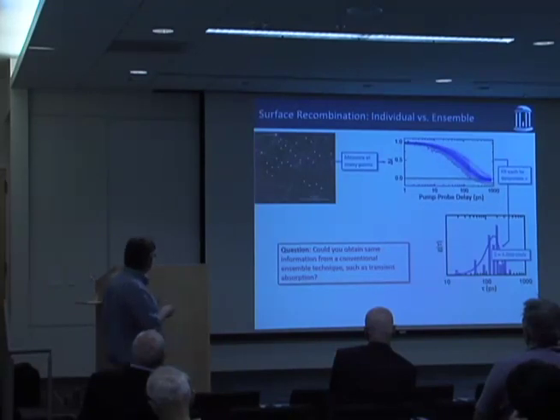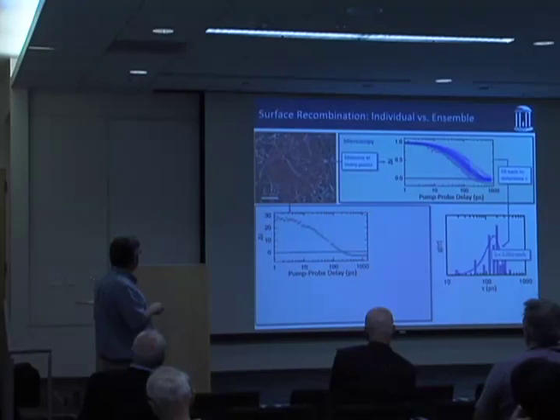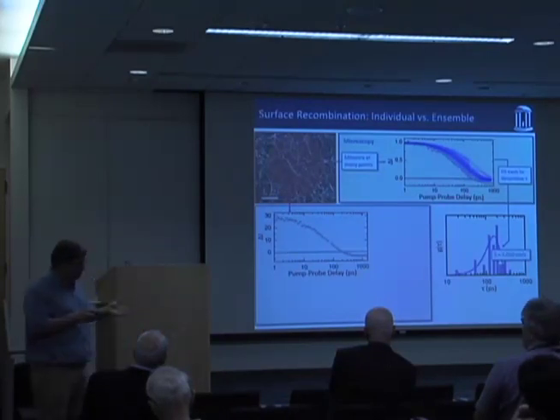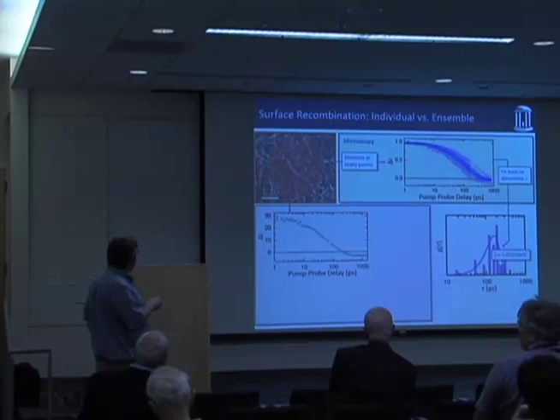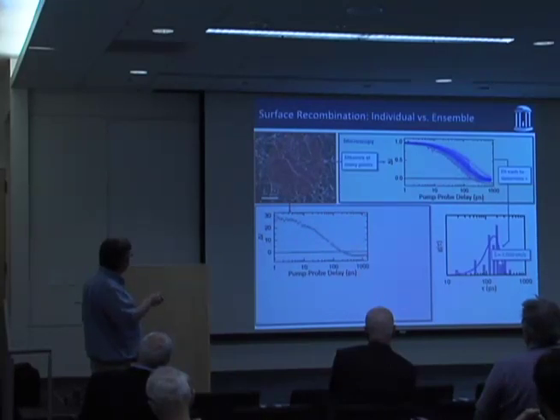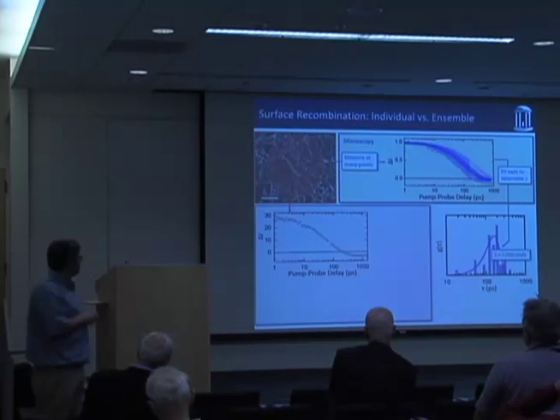And so in our lab, we also do transient absorption. So we took the same sample, exactly the same chip, and we put it into that spectrometer, excited at the same wavelength or nearly the same wavelengths. And this is what you get from that. And this is the ensemble measurement. And it looks similar. These points here are actually those gray points, so they're a little bit faster than what you get from the microscopy.